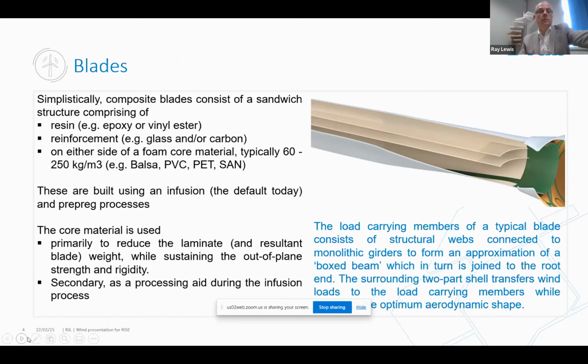And for us, actually, at Diab, and for other core manufacturers, it's actually been a real benefit in some ways because, of course, primarily the core material is in there as a structural core material to actually reduce the laminate weight. But the other part, which is not often seen, is it's acting as a processing aid during the infusion process.